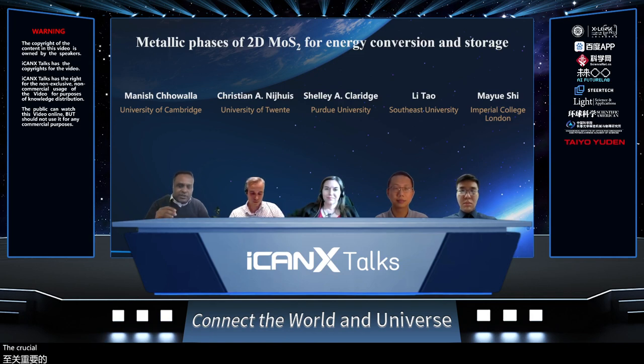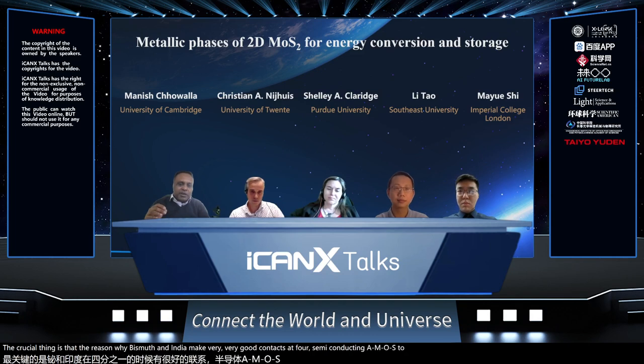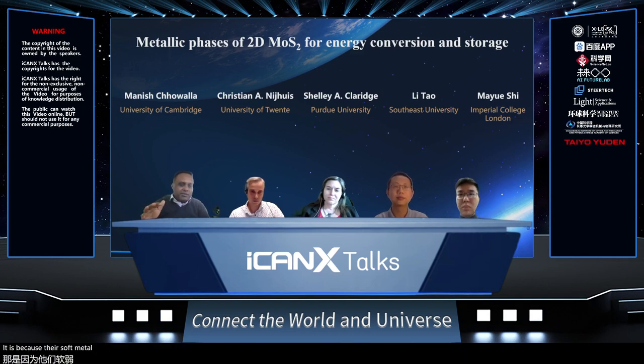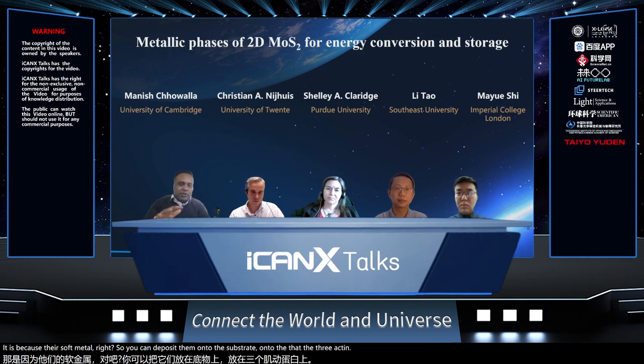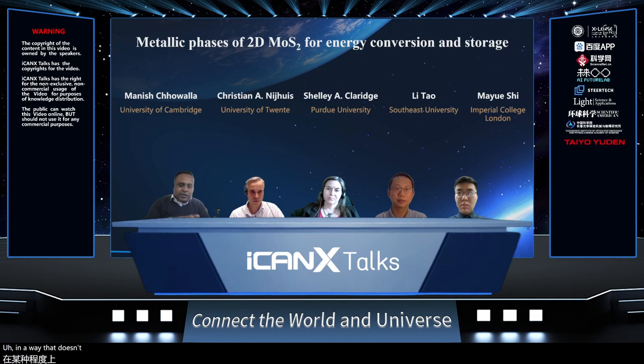But the crucial thing is that the reason why bismuth and indium make very, very good contacts for semiconducting MoS2 is because they're soft metals, right? So you can deposit them onto the three-atom-thick MoS2, or any other semiconducting TMDC, in a way that doesn't cause any damage at the interface and leaves the interface very, very clean, so that the Fermi level is not pinned, right?